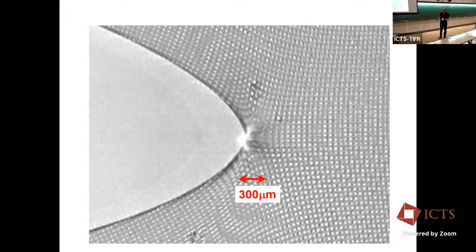This is not trivial to do. But once we have it, it's a great tool because one snapshot gives us the entire strain field. And this also carries with it the reference frame, because each one of these initially was perfectly square. And we know that. And we also can label these, so this is number 1, 2, 3, and so on.